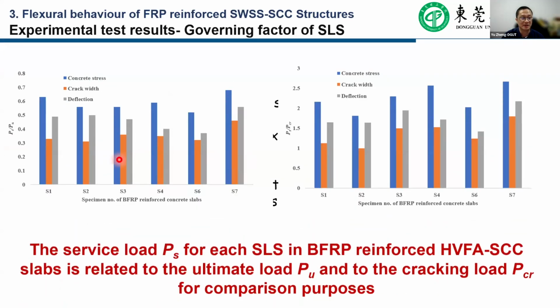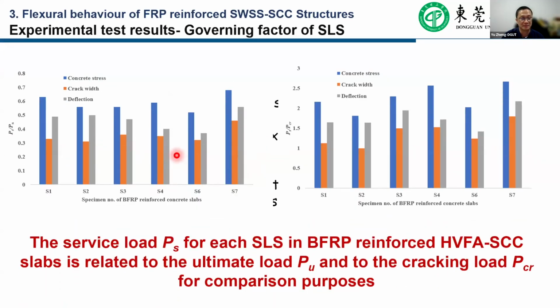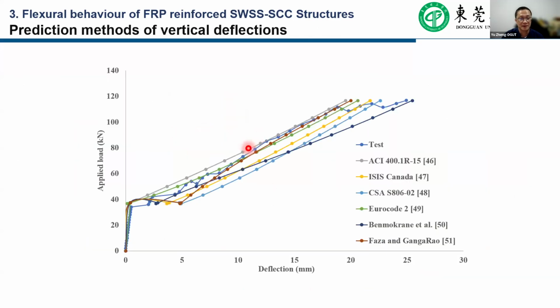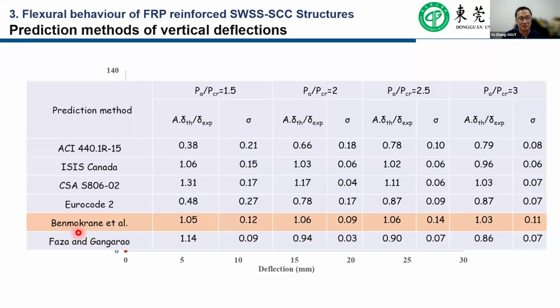In this study, we can get a conclusion that the service load for each service limit state in the FRP reinforced self-compacting concrete is related to the ultimate load and the cracking load for comparison purposes. The crack width can be used for the design of the service behavior. But for the load and deflection response, we can find that most of the current design methods show a good correlation with the test results, especially the model provided by Professor Ben Mokrane.